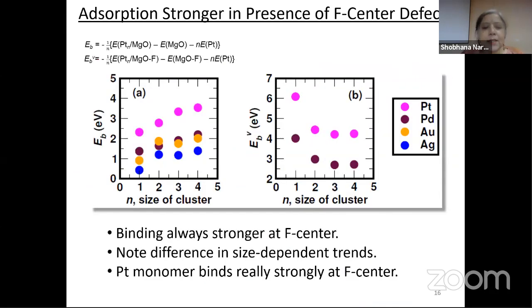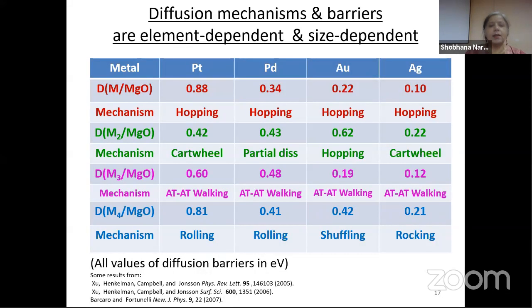Now, the adsorption energy, this is the same thing. It is shown now the trends as a function of cluster size. So this is this binding energy of the cluster to the substrate. On the left, it shows it when there's a defect-free surface. On the right, when there is a defect. And you see that the binding is stronger, but also interestingly, the size-dependent trends seem to flip when there is a defect. Now we are studying diffusion.